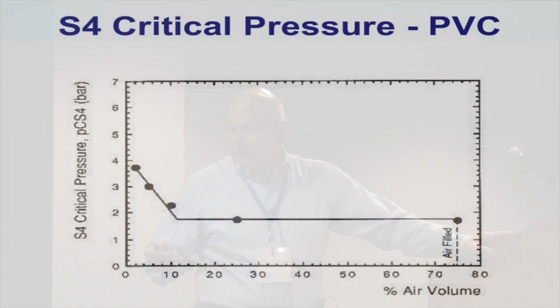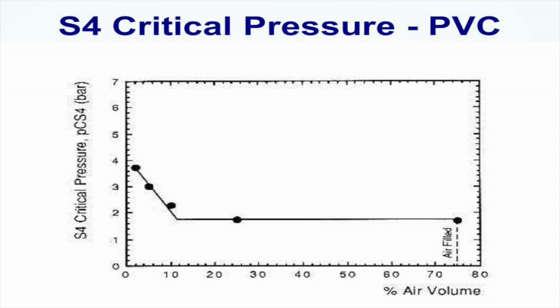Okay, let's take a look now at PVC. This is the data again from Dr. Pat Lieber's critical pressure as a function of the percent air volume. We can see that in 100% water, we get the highest critical pressure, just like with polyethylene. And as we increase the air volume, the critical pressure decreases. We get to about 10% air in water, and it starts to level off.